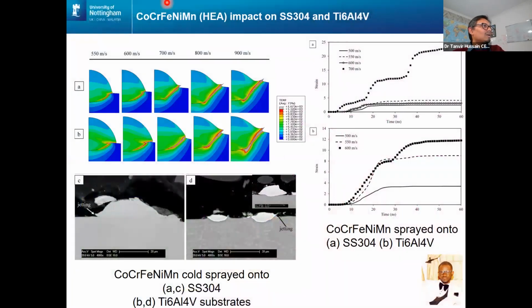So here we are working with high entropy alloy, so cobalt, chromium, iron, nickel, manganese. So John, who is still doing his PhD. So what happens in the cold spray? You have a particle hitting a substrate at very high strain rate, and it forms a metal jet. That metal jet, the conventional theory was, removes the oxide, and as a consequence of removing the oxide layer, you form a metal-to-metal bonding.